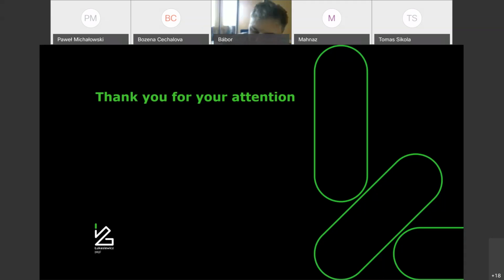Maybe I can start. Thank you very much for a nice presentation. It looks like you have solved all the SIMS problems like tailing, mixing, etc. So my question is, if you could be a little bit more specific regarding the energy which you use for the sputtering and polishing, or if the energy is the same, because as it's known, once you reduce energy, you also reduce the sputtering coefficient, and you have shown us profiles with, I would say, hundreds of nanometers or something like that. So what energy you use for the sputtering, if you could be more specific regarding the X-ray mirrors and things like that.